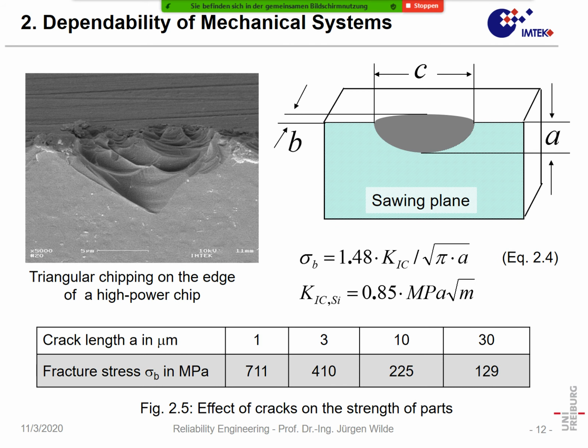Here I give you some examples from our research work. That is a crack on silicon. So if you dice silicon, you generate cracks, and when you regard such a crack, when you know how deep it is, so the crack length, then you can compute what the stress is in your part. Okay,